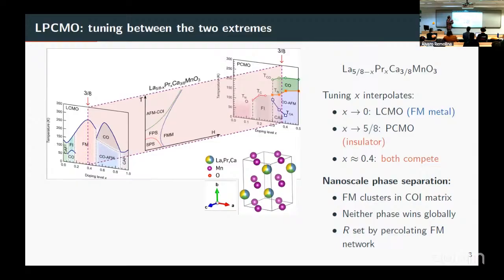this. So the phase diagram of the material I'm going to talk about today, which is lanthanum, praseodymium, calcium, manganese, we call it LPCMO. It has a complex phase diagram. This is temperature, this is field, and depending on where you are in this phase diagram, you have something that is completely antiferromagnetic, you have something that is ferromagnetic, but the magnetism there is completely strange.